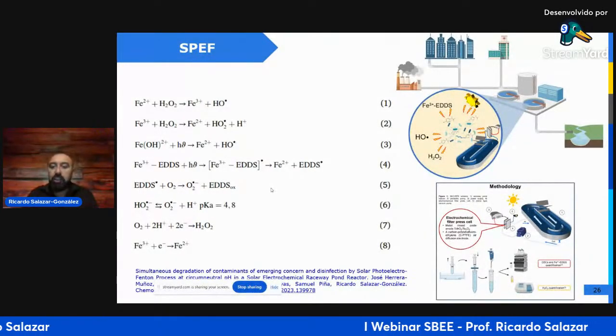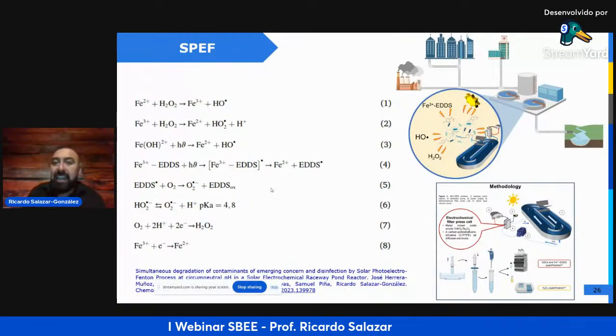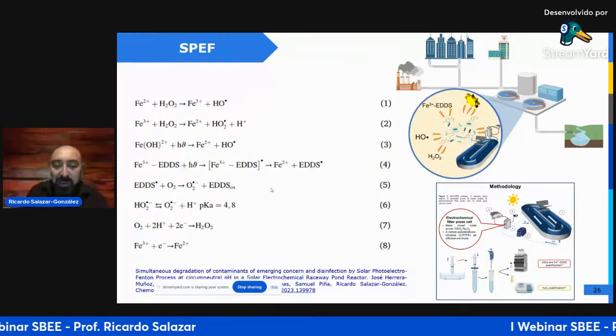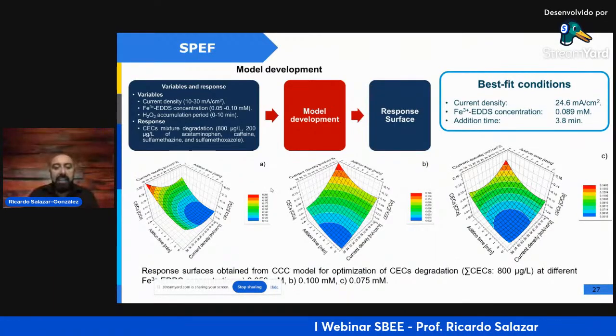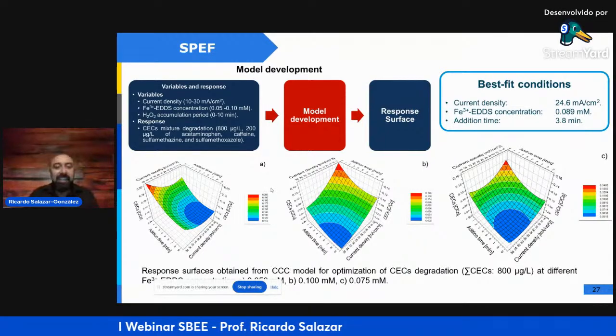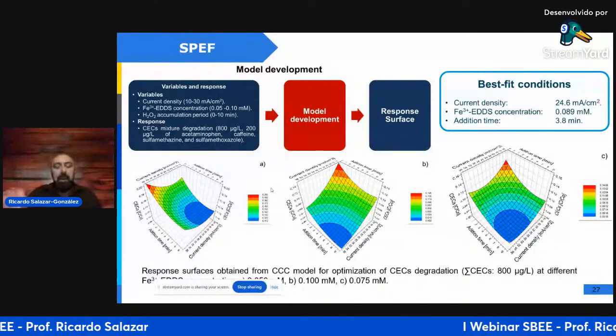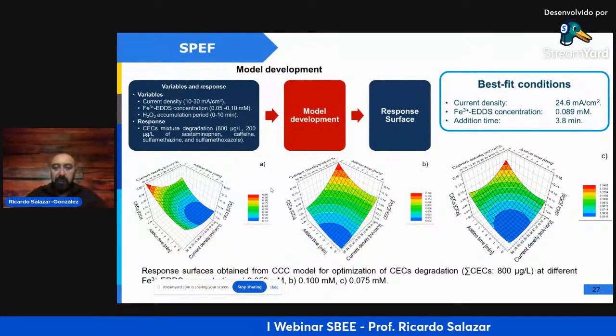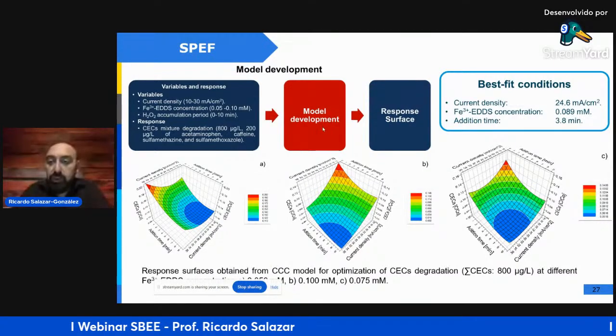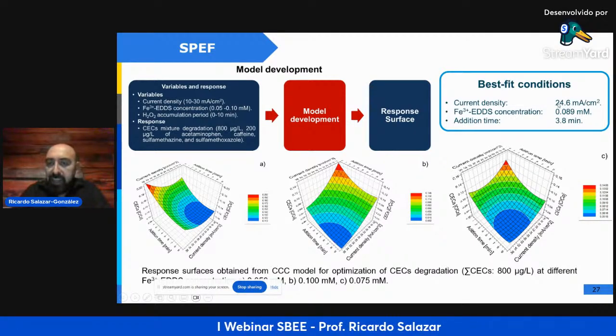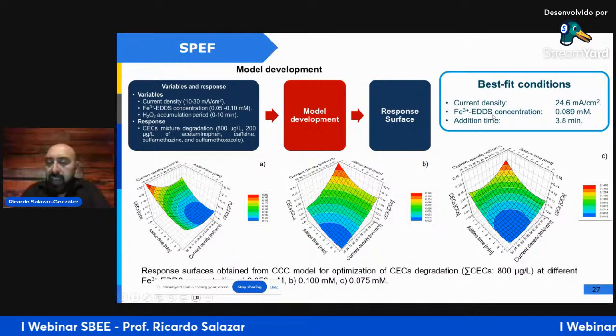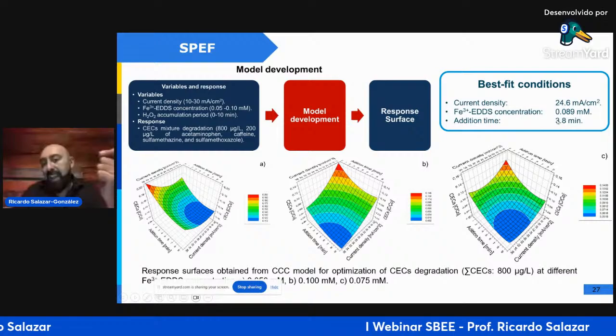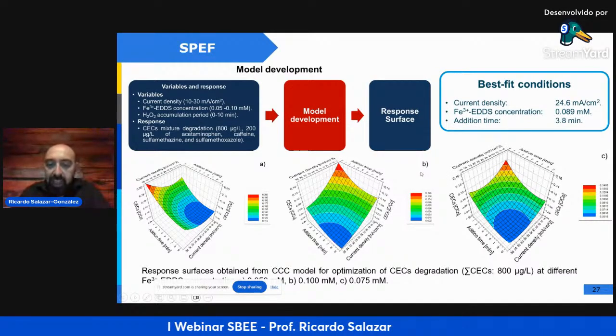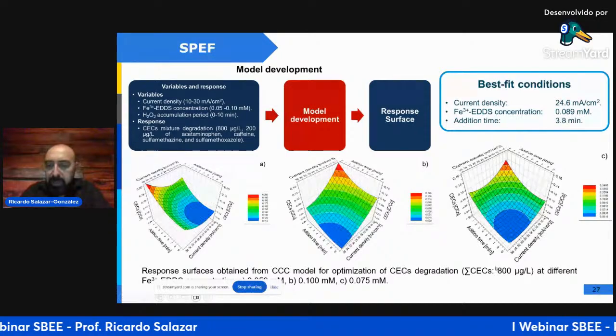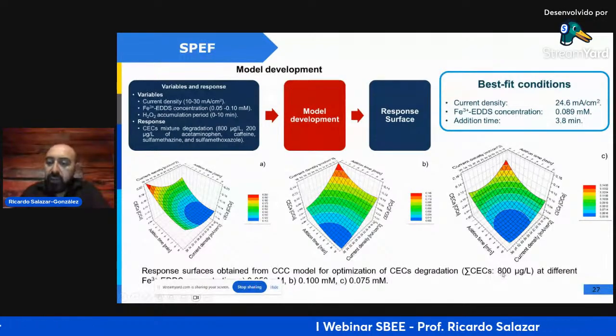So we study the elimination of contaminants of emerging concern in very real experimental conditions. For this study, we prepared a chemometric analysis. So we studied all of the variables and looked for the best experimental conditions. So we determine the best current density during the process, the concentration of the iron complex, and the time when we have to add the complex to the solution. And we have a mixture of contaminants of emerging concern of 800 micrograms per liter.